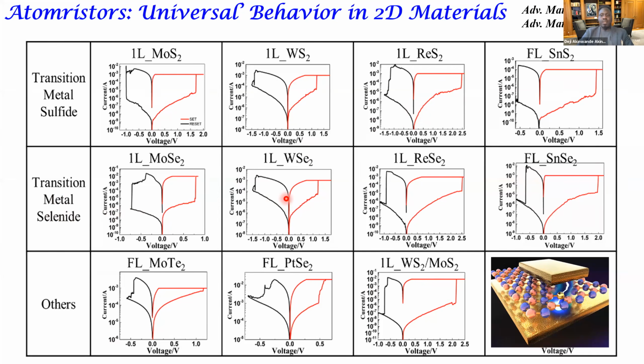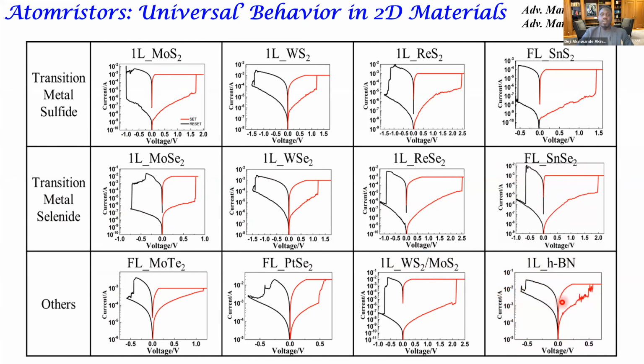Transitional metal selenides, also all the samples we could get hold of, we also saw this effect. The other materials I'd like to point out are heterostructures, which show this effect as well. And then the thinnest of them all is hBN — one layer hBN, a 0.3 nanometer active layer, also shows this effect.